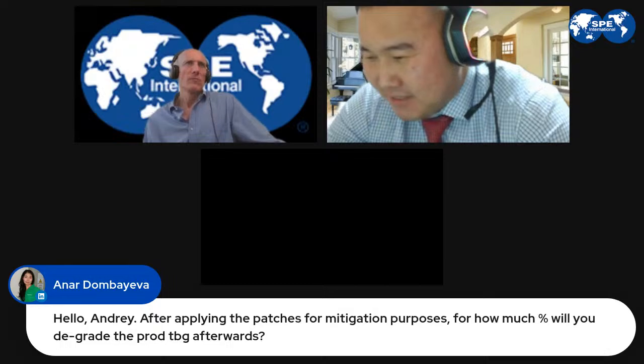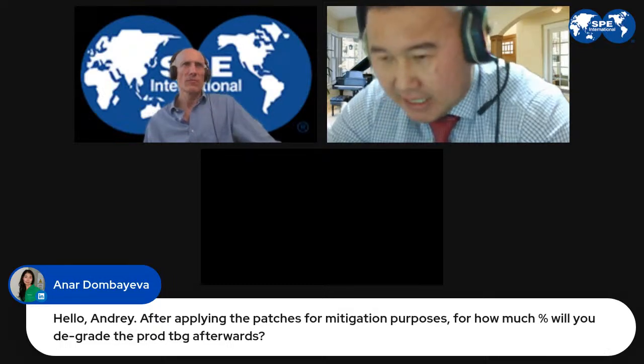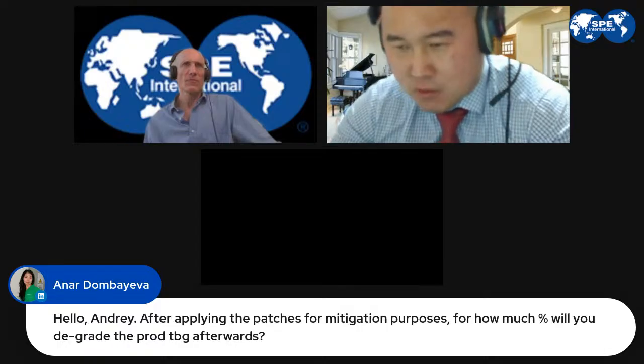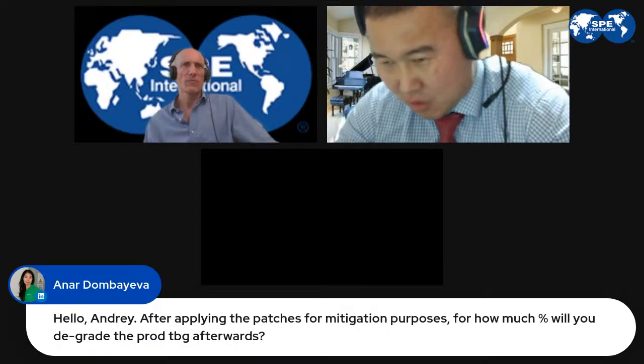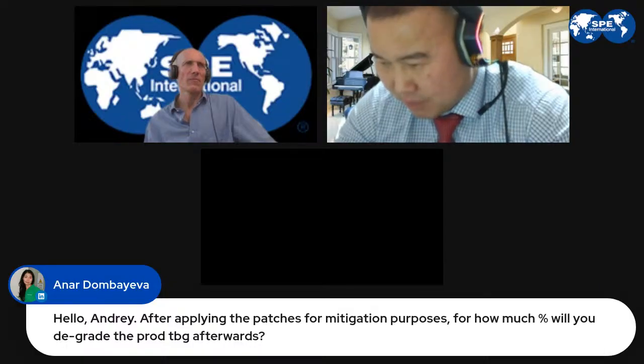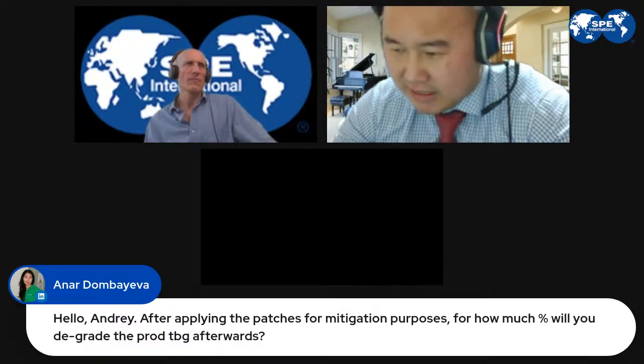Look, there is a theory and there is a practice. There is an equipment working pressure rating provided by the owner of the tubing patch or straddle packer. And then it's up to you. As a minimum, obviously you have to test the tubing to the maximum shut-in tubing head pressure you can experience during your well life. Plus, you need to add some extra pressure for killing purposes, so we add 500 psi. I believe that's the minimum. And if your equipment working rating is less than that, then don't even apply. Okay.